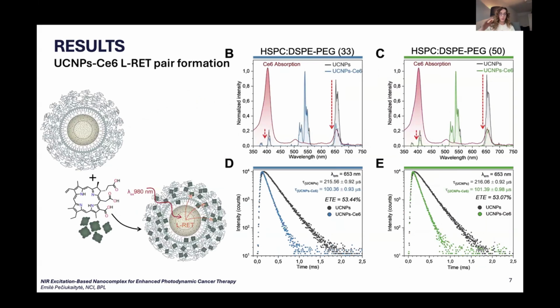Since chlorin e6 is amphiphilic, the phospholipid coating should act as a nanopocket, a little pocket that stabilizes the chlorin e6 molecules on the nanoparticle surface. The main question we wanted to answer was whether non-radiative energy transfer was happening, specifically luminescence resonance energy transfer, within this nanocomplex. Spectral analysis revealed decreased upconverting nanoparticle emission intensity in both the UV and red regions, which overlap with the chlorin e6 absorbance spectra. This only indicates, but we cannot be completely sure, that energy transfer is happening.